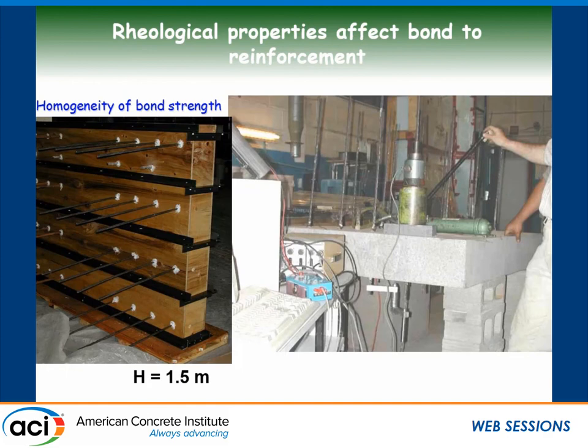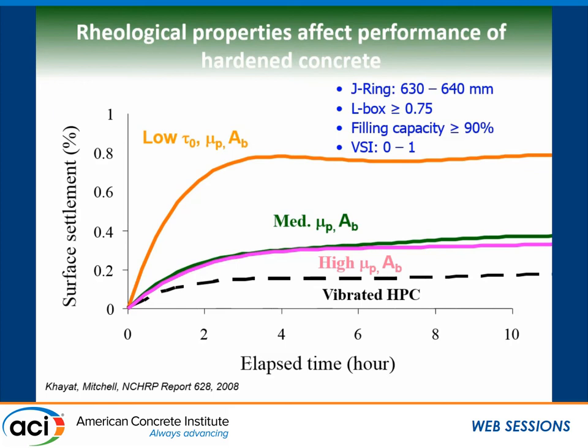And this is the same work, also 1.5, but here we're dealing with also pre-stressing strands. And this work was done a few years ago for an NCHRP project where we specifically took SCCs that have very, very good functional requirements characteristics. So performance characteristics: slump flow is high, passing ability, L-box, filling capacity is extremely high, VSI, visual stability index, really good. But if you test the surface settlement, which in my opinion is the best test out there for static stability, you can differentiate a lot between the behavior of these concretes.